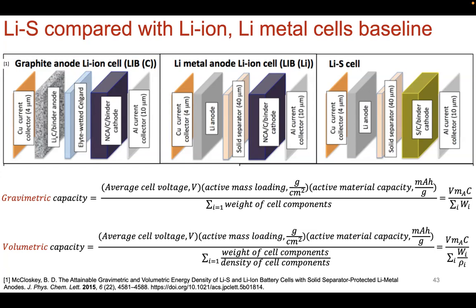lithium thiophosphate based separator. And then when it comes to lithium sulfur cell, it's quite similar to that of the lithium metal battery. You also have a physical separator here, but the sulfur to carbon to binder ratio is really dependent on what you're trying to achieve. If you're trying to increase gravimetric capacity or you're trying to increase volumetric capacity, it's a different ballgame, depending on what your objectives are and how you load the cell.